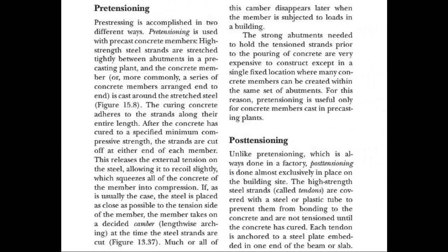With pre-tensioning, typically used for precast concrete members such as floor beams or girders, the steel strands are stretched in a form — usually off-site. The steel is stretched to a specific tension, concrete is poured, allowed to cure, and then the strands are cut off at either end, releasing the tension and creating that camber. That's why sometimes precast concrete structural floor slabs or beams going down the road have that little curve to them — maybe an inch to a half inch.